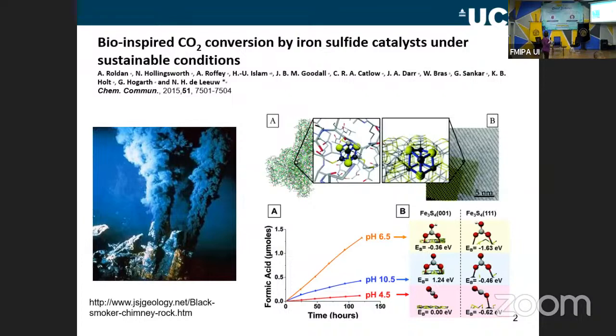So what we did is we made this iron sulfur material, put it onto an electrode, and applied a negative electrode potential to carry out reduction in the presence of carbon dioxide in different pH solutions. Over time we measured how much product was made, and the product was mainly formic acid. So you could reduce carbon dioxide to make formic acid on the surface. An important thing to note is that we did this reaction over a very long period of time, and the amount of formic acid we made was very small. So these materials are catalysts, but they're very bad catalysts, okay?